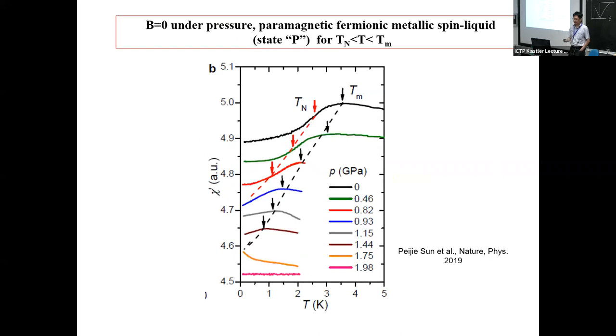Okay, in that paramagnetic window, this behavior was also observed under pressure, as you can see that between this Néel temperature and the maximum temperature of the susceptibility, there is a finite window in temperature range where you see this paramagnetic or spin liquid-like behavior.